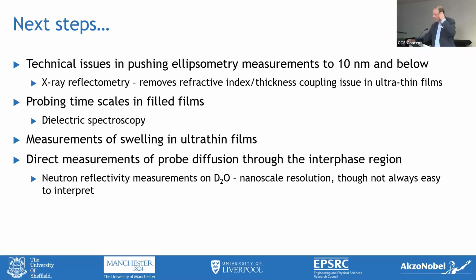Your old company gave me a nice CASE award to study it with my student Anya Wareham, and I think she demonstrated quite convincingly that if you measured the temperature dependence of the adhesion process in PET carefully, you could see diffusion proceeding below the glass transition temperature.